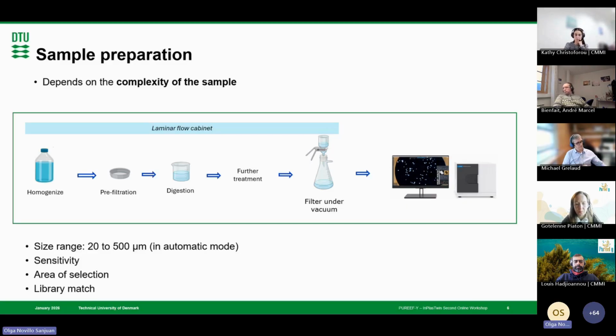There is another parameter that can be modified in the LDIR, and it's the sensitivity. But I will go back to this later, because more sensitivity, of course, means more things are identified. But in my experience, increasing sensitivity doesn't always give you better results, because it can actually lead to more artifacts. So in my workflows, I usually leave it as it is, at middle sensitivity. And then you have to select an area in the sample and then the LDIR uses its own algorithms to match the sample spectra with the reference spectra, like in methods like FTIR and even Raman.